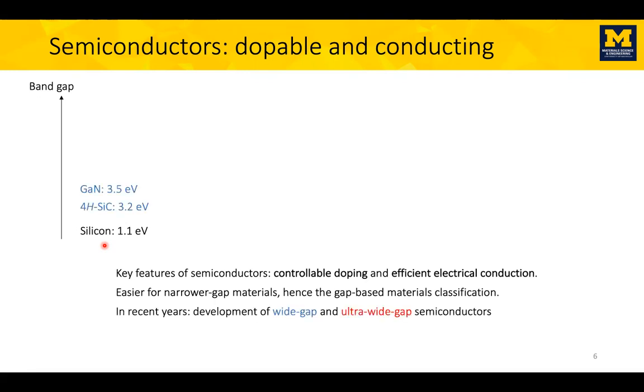So in recent years, there's more and more effort towards developing semiconductors with band gaps wider than those of silicon. I'll mention here silicon carbide in the 4H polytype and gallium nitride, with band gaps of around 3 electron volts. These two are commercial, especially when you want to go to high power. Silicon is great when you work at 5 volts, but if you want to work at 500 volts, silicon becomes problematic. Silicon can't tolerate 500 volts. You would fry a typical microchip.